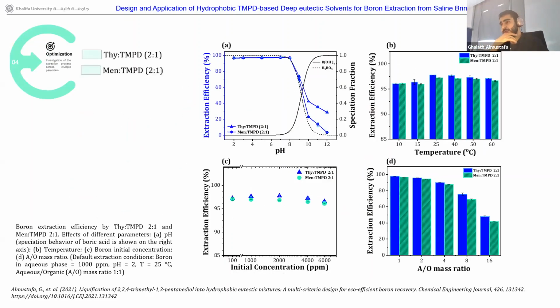But again, since we're done with the design part, to show you the application part, we tested those DESs for different parameters in the boron extraction process, such as pH, temperature, initial concentration, and the aqueous to organic mass ratio. And you can see that we compared to the literature what we had before, and it was a superior performance, mainly due to the TMPD role in this eutectic state that has been granted with the DES.